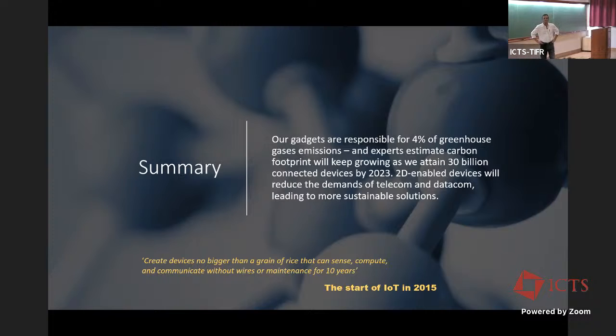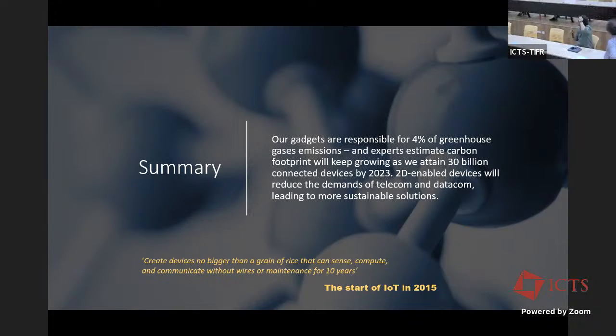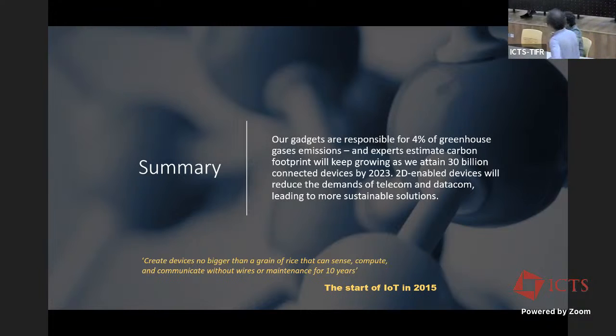So you gave this example of this invisibility cloak type thing. Where did the actual semi-metallic character of graphene enter in? It's a very good question. I didn't elaborate that properly. It's a smallness of energy. You see, you're talking about 0.1 electron volt photons. But look at most semiconductors, most materials have much larger band gaps. Essentially what happens is you can change the emissivity dynamically by simply doping graphene and covering that energy range, which is impossible with most materials that we know.